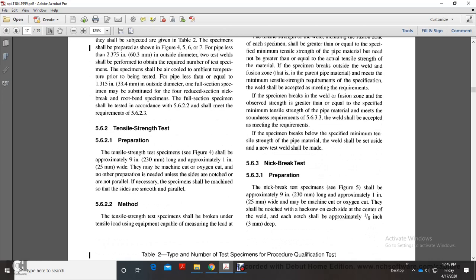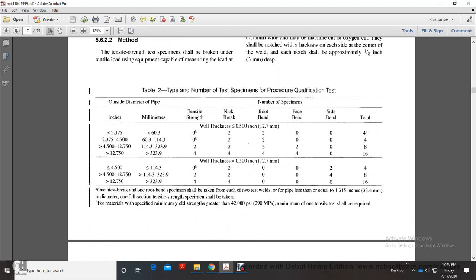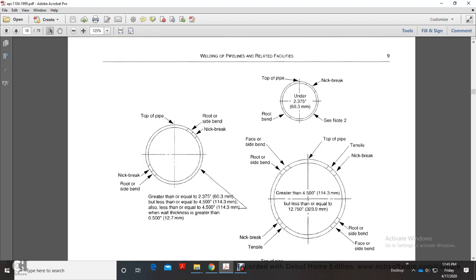5.6.3 The nick break test. Preparation. The nick break test specimen, Figure 5, shall be approximately 9 inches long by about 1 inch wide and made by machine cutting or oxygen cutting. It shall be notched with a hacksaw on each side at the center of the weld. Each notch shall be approximately 1/8 inch deep. Type, number of test specimens in procedure qualification testing, and then it shows